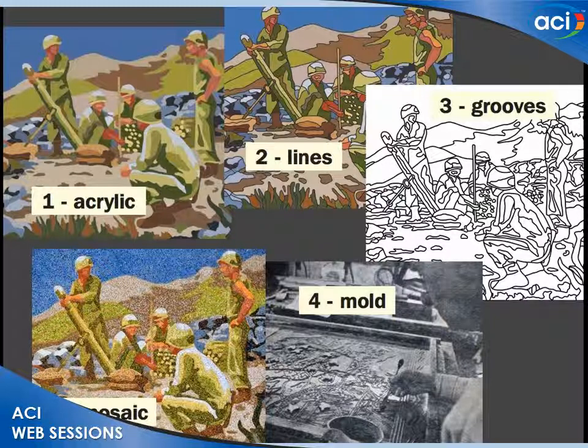They then remove her drawing and put chalk to identify those holes, and then used a scribing tool to carve grooves along every line. Those grooves are about 1/8 of an inch deep. They then put a mold release agent and cast another plaster mold on top of that model. So they then had, as you see in number 4, a plaster mold that they would use for casting the concrete. They used a form release agent.